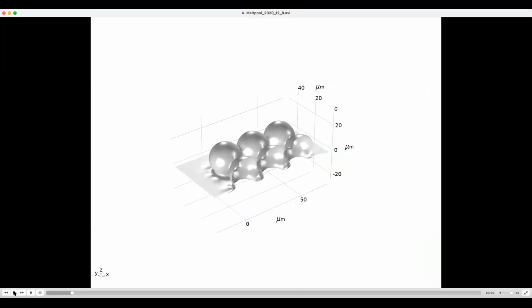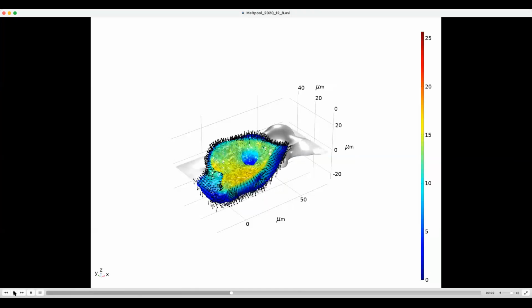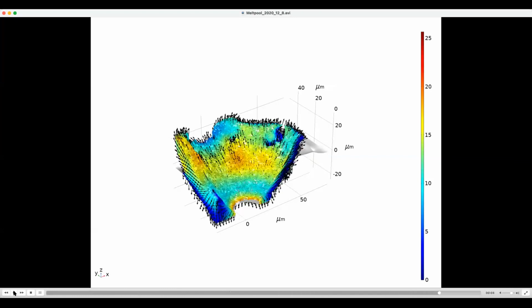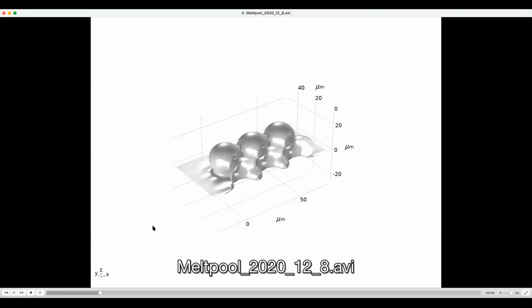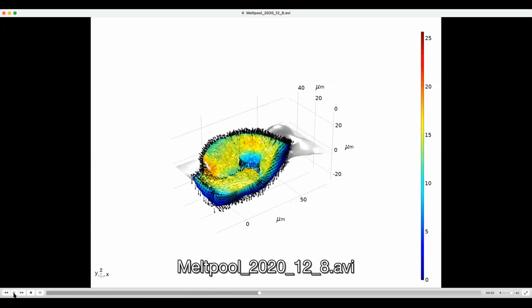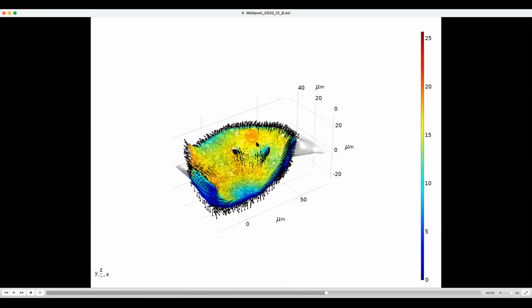The laser comes in and it's heating, and it creates a divot due to the pressure of the laser melting and vaporization. If I pause it here, you can see there's a little divot in the print. This is because the molten metal is getting blown by vaporization. The metal underneath the laser is boiling, and that's pushing the metal down. It's kind of like if you blow on a bowl of soup, you'll have a little divot there. Every once in a while, these divots collapse and trap some air inside the part.